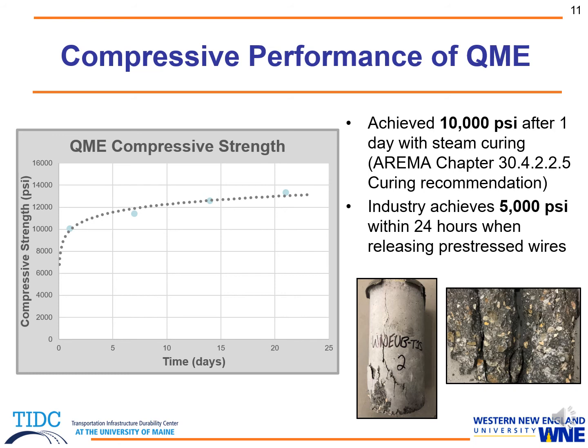Also, it's noted that the industry tends to achieve right around 5,000 psi within 24 hours when releasing their pre-stressed wires. So the strength that we achieved is double that of what they're seeing in industry.